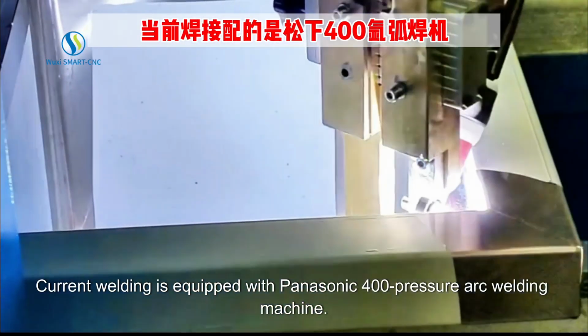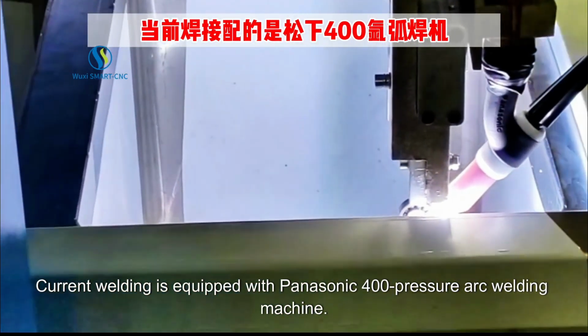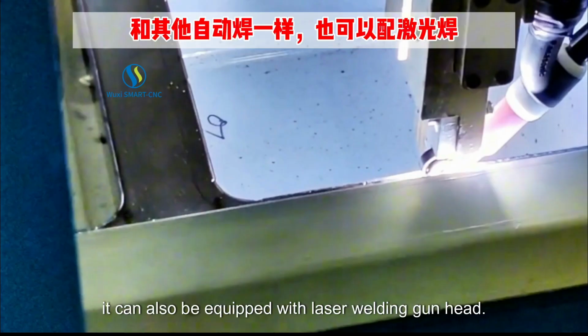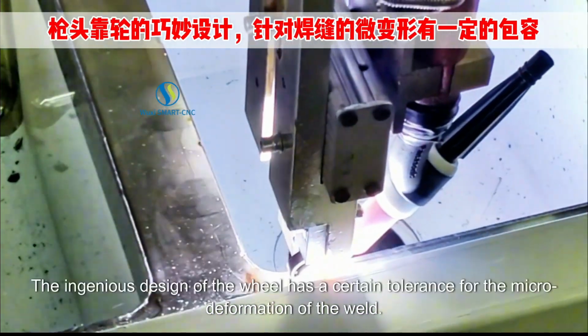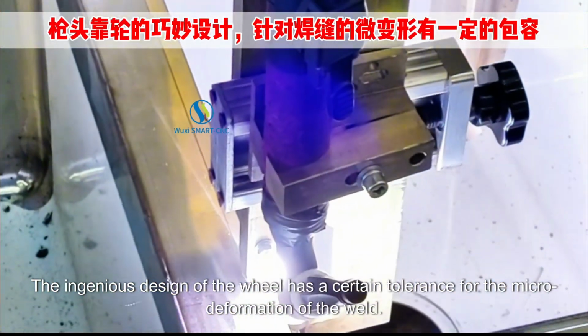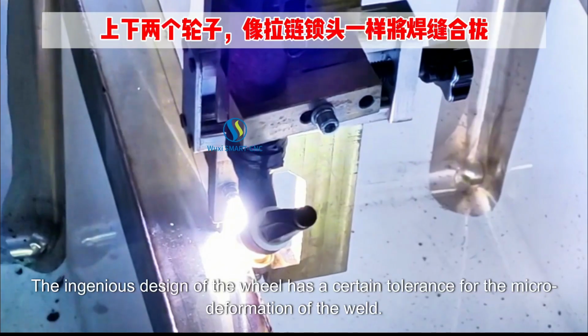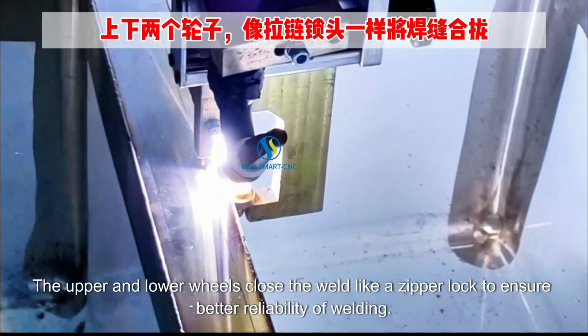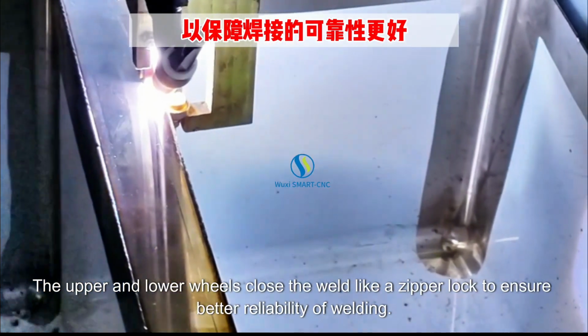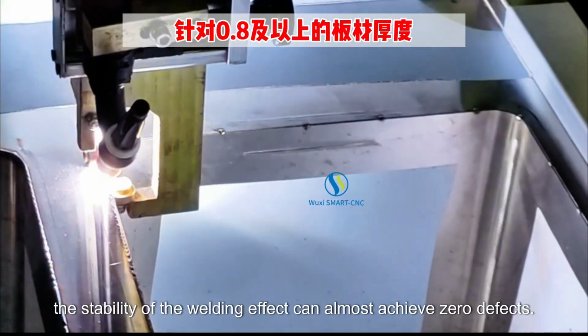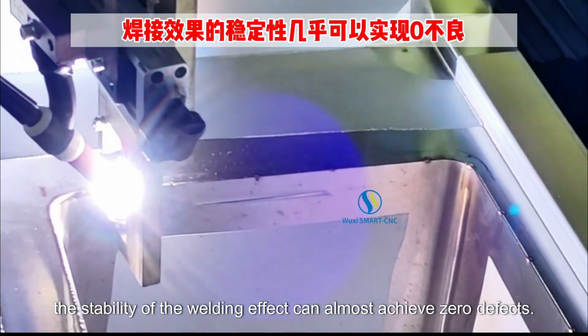Current welding is equipped with Panasonic 400 argon arc welding machine. Like other automatic welding, it can also be equipped with laser welding gun head. The ingenious design of the wheel has a certain tolerance for the micro-deformation of the weld. The upper and lower wheels close the weld like a zipper lock to ensure better reliability of welding. For plate thicknesses of 0.8 and above, the stability of the welding effect can almost achieve zero defects.